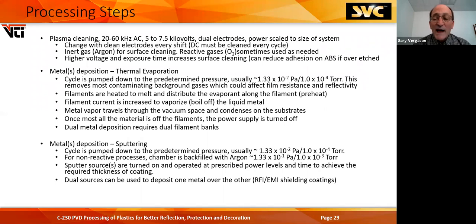First thing we do is plasma clean the parts. It's a range between 20 to 60 kilohertz AC, 5 to 7.5 kilovolts. We use two electrodes that are insulated from the vacuum chamber, and the power is scaled up to the size of the machine. We change the electrodes every shift. The electrodes are different geometries, and they just quarter turn and lock. With DC, like I said earlier, you have to cover them with aluminum foil. In AC, you're switching back and forth, so you get a little bit of self-cleaning.